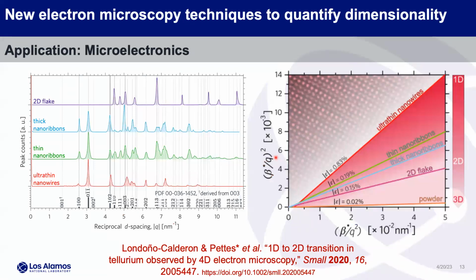And so we said, for this characterization technique, why do we have to go with the textbook example that you can never do quantitative diffraction in an electron microscope because uncertainties are like 2 to 5%? So we said, let's get that uncertainty better by using the new methods that we came up with our collaborators at Berkeley, to do patterned probe and to apply some techniques from astronomy on registration of disks. So we do disk registration on the diffraction peaks and quantify that in the way that you would do on X-ray diffraction. Obviously this doesn't look as sharp as X-ray diffraction. One reason is these are nanomaterials, so there's broadening. The other reason is it's not as clean a way to do the measurement as X-ray diffraction. But we have these scans on like 5 nanometers of material, so a much smaller localized length scale.